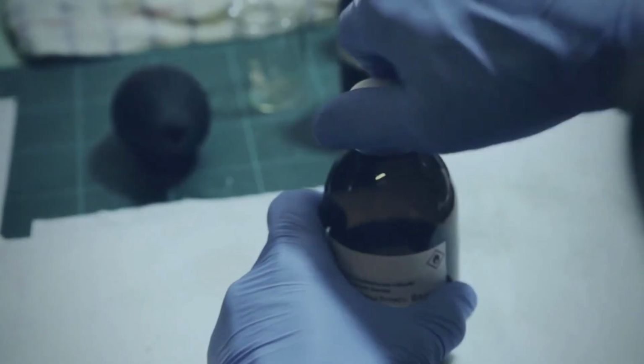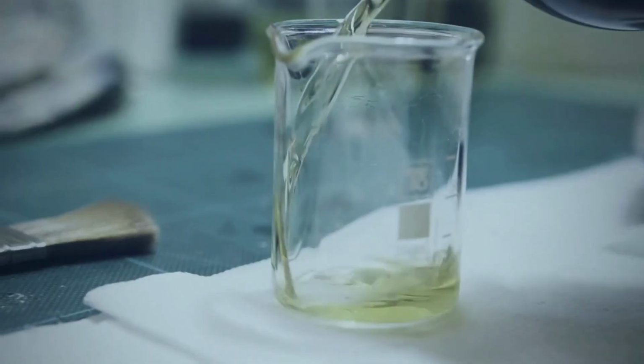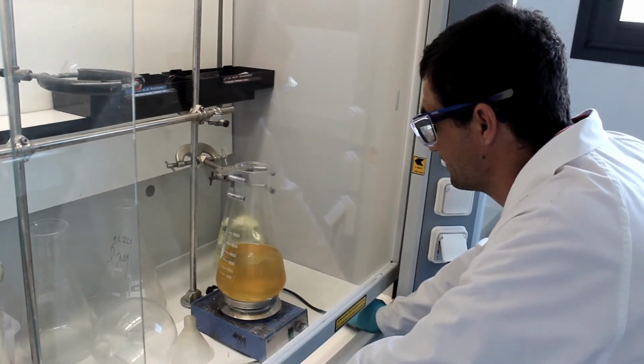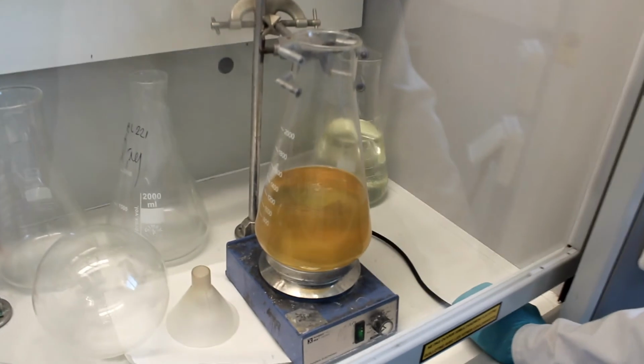Based on the specification from the implementation process and the end users, we finally selected the bio-based epoxy resin made from vanillin and phloroglucinol as the most relevant one for the application. We scaled up the synthesis of both resins at 20 kg scale in order to be able to implement automatic part demonstrators by wet compression molding. The composite part obtained from these epoxy resins and PLA fibers or flax fibers exhibited similar thermomechanical properties to the one prepared from the petrol-based epoxy resin.